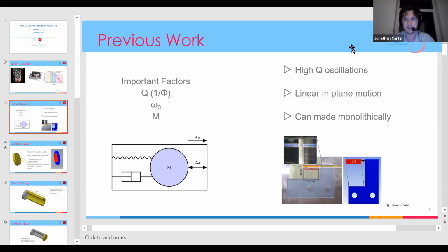Yeah, and by making it monolithically, he was able to preserve the relatively high quality factor of fused silica in his design and achieved quite a nice performance. But this design was still very small, and it had a resonance frequency of about 10 kilohertz. I know his group has made some progress on this, but there are now a few groups trying similar ideas and asking how we can adapt this kind of design to be useful for gravitational wave detection.